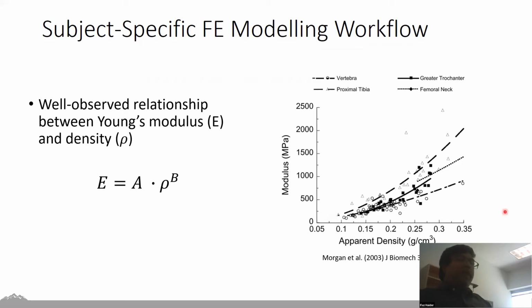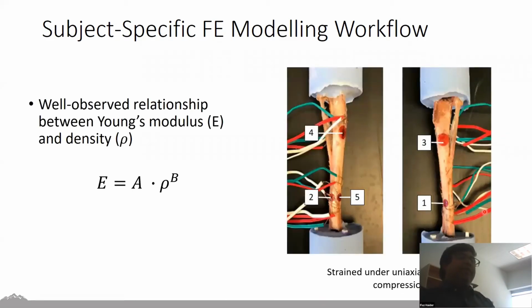And you can see why if you pay attention to this data that I'm showing on the right, which was done by Morgan et al. Here, they tried to quantify the density modulus relationship using all human bone just from different sites of the body. And as you can see from this graph, they get a different relationship depending on where on the body they actually took their specimens from. Of course, in our case, we have to contend not only with that, but the fact that we're talking about rabbits and not humans. And we certainly weren't able to find data that looks like this for a rabbit tibia. So we did the next best thing, and we estimated A and B based on some experiments.